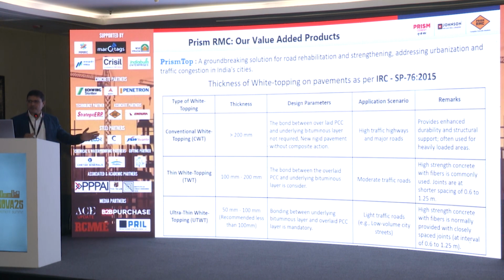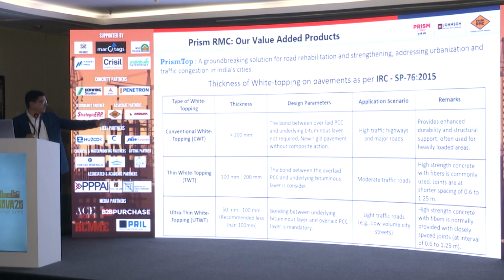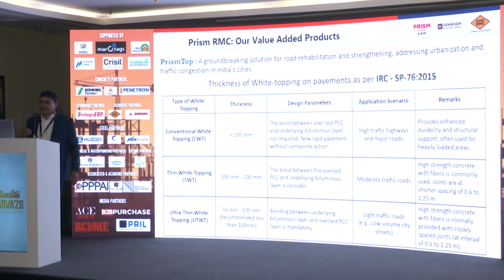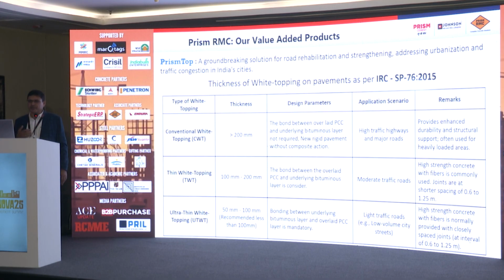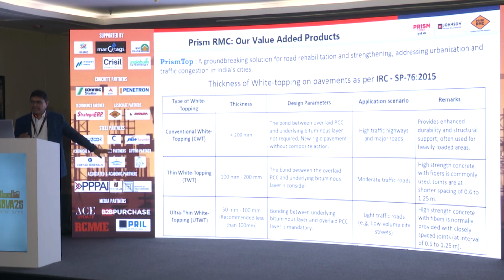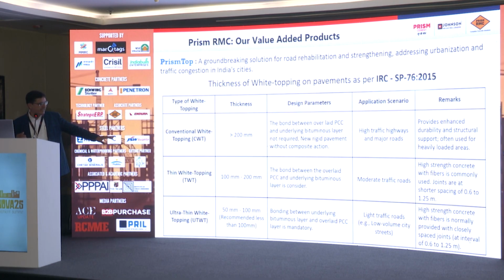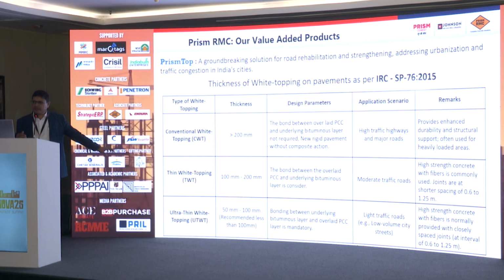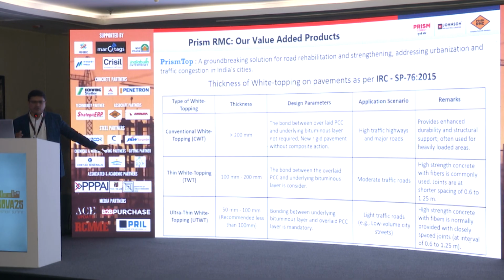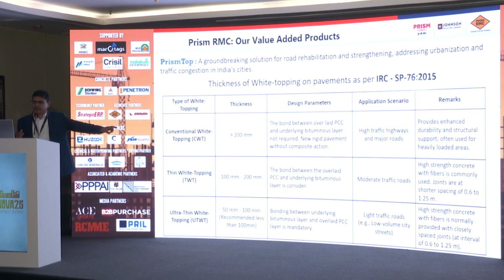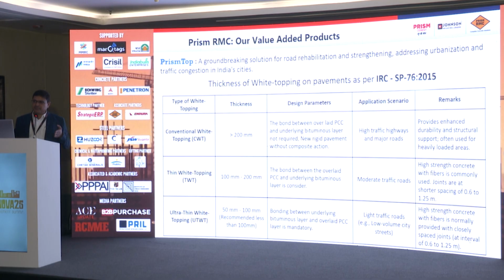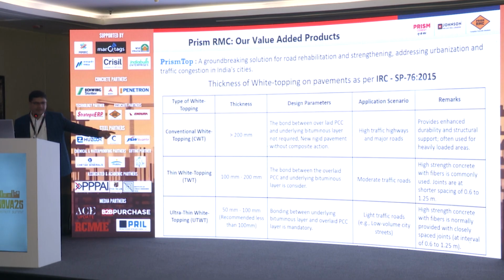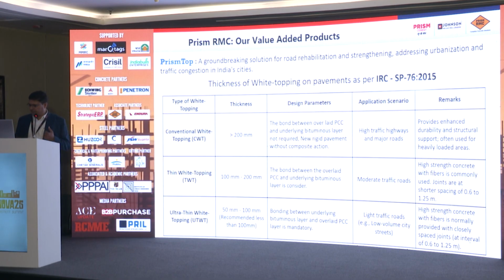So we have products for M30 to M40 generally for the conventional topping, and high strength concrete, generally M60 and above, with fibers. The only addition is that we need to do the bonding when the thickness of concrete is less, for ultra topping or thin ultra topping. The joints are important to minimize or control shrinkage cracks. For ultra topping, 0.6 to 1.25 m joints are required.